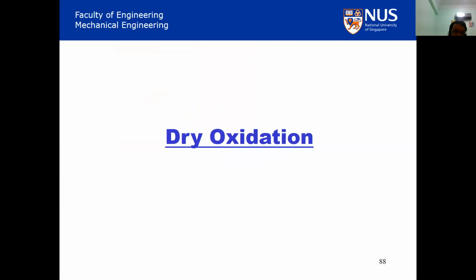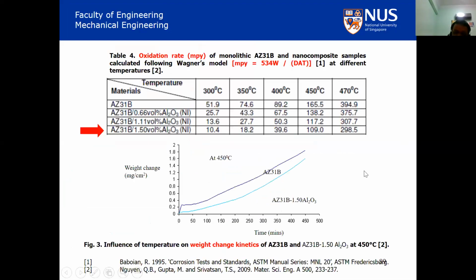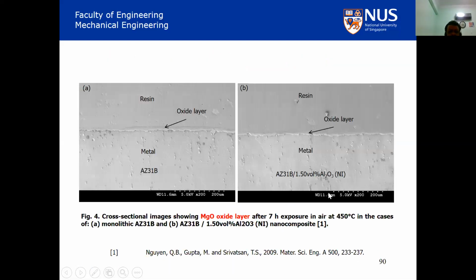Now, how about when you put a material into the application? It should not corrode. So how do these nanoparticles affect the dry corrosion or the oxidation behavior? We did work at a number of temperatures. If you look at this graph, the AZ31 commercial magnesium alloy shows more weight change when compared to AZ31 with 1.5% Al2O3 particle. This can be attributed to the refined microstructure of the material. If you look at the picture on your left hand side, you see there's an oxide layer which is a bit thicker, and on the right hand side, which is of the composite, it is more compact and thinner.